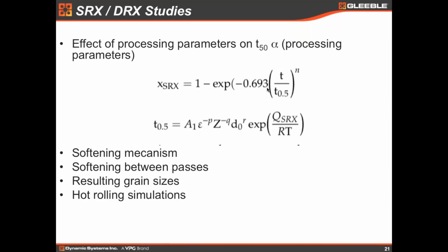Well, usually, as a rule of thumb, as you increase the level of solutes or impurities, you decrease the velocity of the grain boundaries. So the recrystallization will be affected because the kinetics will slow down as we have more impurities. For example, let's get a practical example. If you have pure aluminum, let's say 5 nines aluminum, very pure, it recrystallizes below ambient temperature or at ambient temperature. Also, metals like lead have dynamic recrystallization at ambient temperature. But this is for pure metals. As you add impurities, the recrystallization temperature starts to increase and the kinetics start to become lower. Okay, thank you.